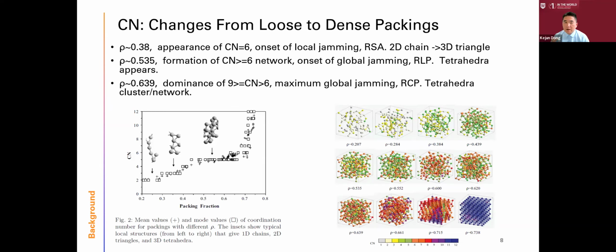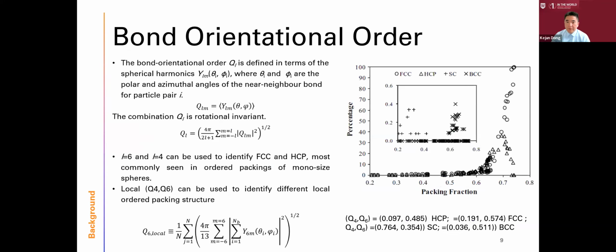And then when the average coordination number reaches 6, which is a normal case, we can see the connection of the tetrahedra. So you can see that using different structure descriptors, we can understand the structure change and the local structure, and how the local structure affects the whole structure.